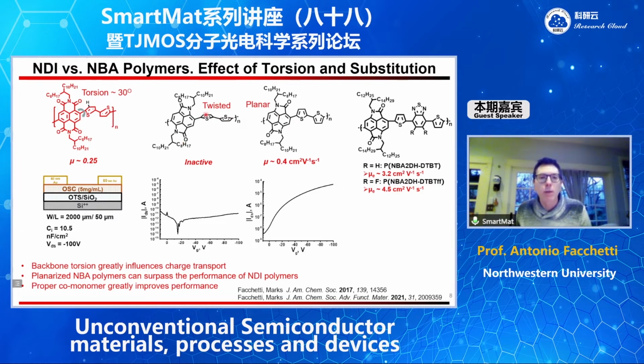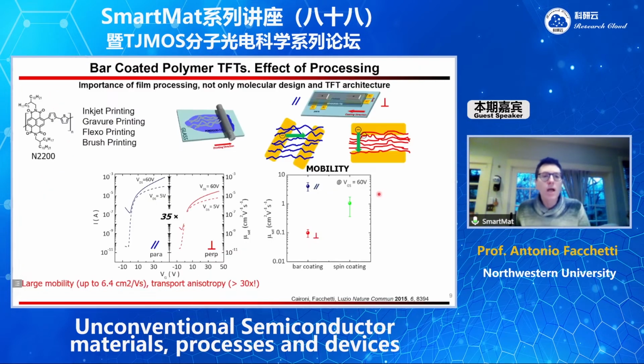And this polymer is actually more twisted than the first polymer and is an inactive polymer. Instead, the second polymer, which is much more flat, when measured in the same condition, has a larger mobility. And then if you use the right comonomer, you can increase the mobility even to a greater extent. Okay, so from chemistry, there are still things that can be done to improve the performance of these materials.